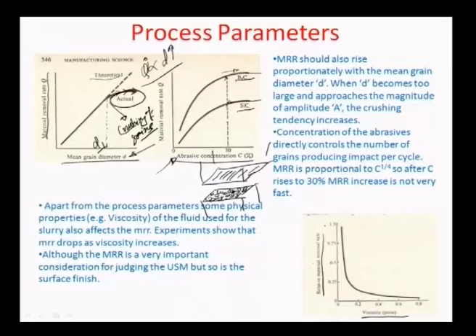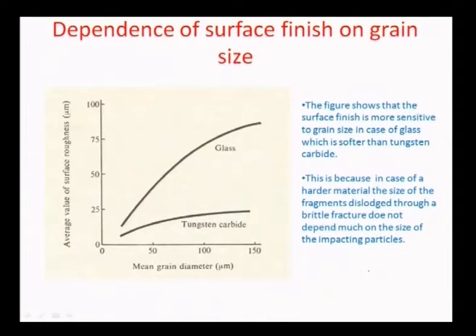would not be easily dissolvable in such a situation. So the diffusion gradients that need to be established should be very high for the debris material, which is formed because of the indentation and the brittle fracture, and does not get carried away very easily in that case. So therefore, with an increasing viscosity, as you are seeing, there is a relative reduction in the material removal rate, as can be illustrated from this trend here. Very important to know that if the viscosity is higher, the removal of the material debris would happen at a lower rate. So that is in a nutshell what some of the operating trends would be.